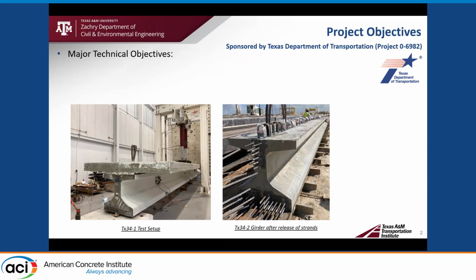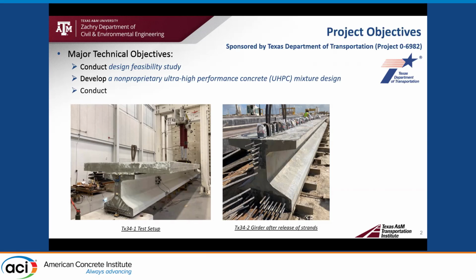What you see here are the finished cast-in-place deck slab and the UHPC girders, Specimen 1 and Specimen 2, in the field. First, we had to conduct a design feasibility study to identify target properties that would best optimize UHPC design for bridge girders when compared to conventional concrete girders. Having identified those properties, we had to achieve those by developing a non-proprietary UHPC mix, and then conduct material level and full-scale tests on specimens developed from that mix.